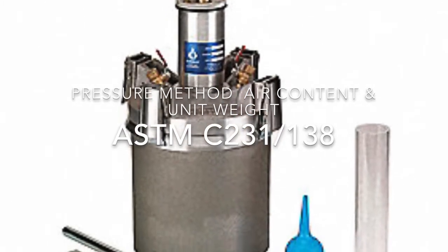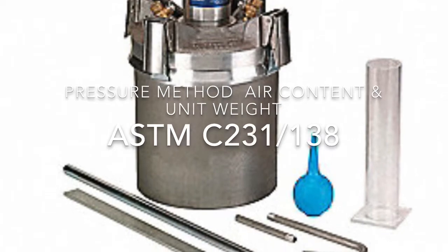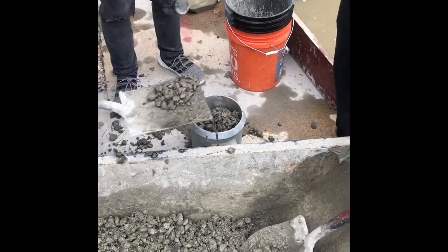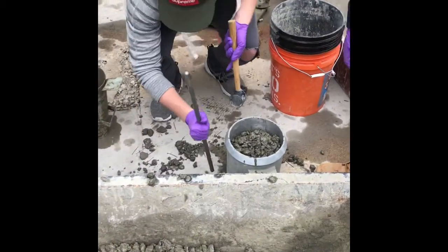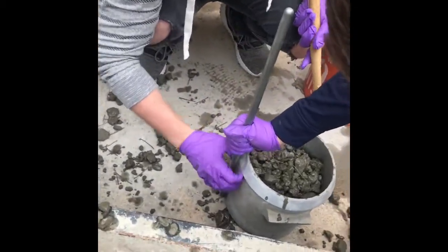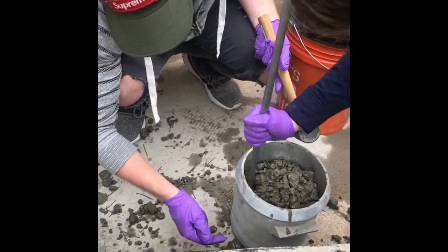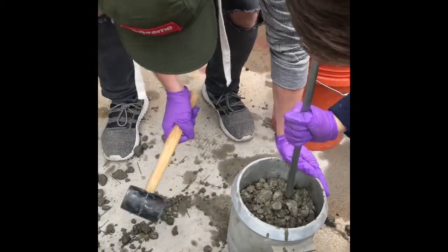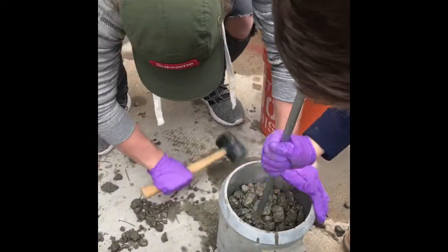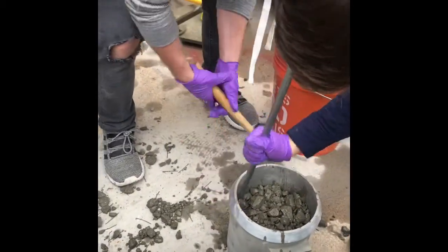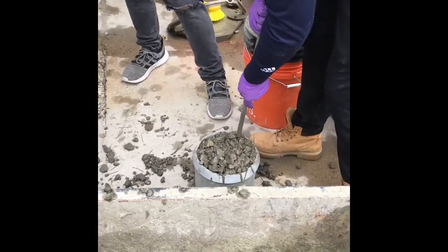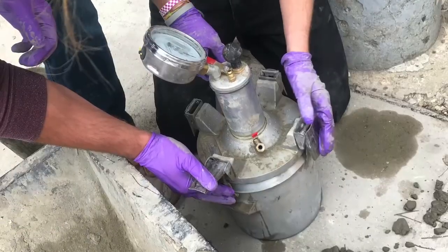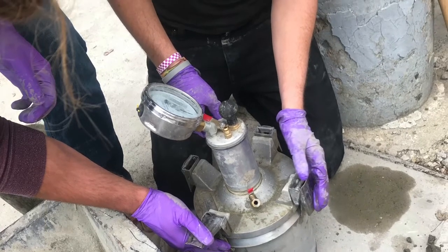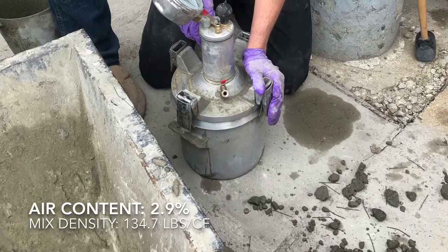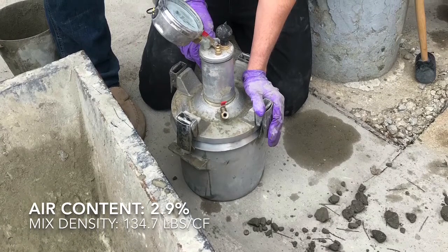Next came ASTM tests C231 and C138, pressure method air content test and unit weight. By using a measuring bowl of known mass and volume, we used a pressure gauge to measure our concrete's air content via water insertion into the bowl. First, we filled the container with the appropriate method of levels and rodding. Then we clamped the lid on to insert water and read the pressure gauge. Our air content was found to be 2.9%. And since we knew the mass and volume of the container, we found our mix density to be 134.7 pounds per cubic foot.